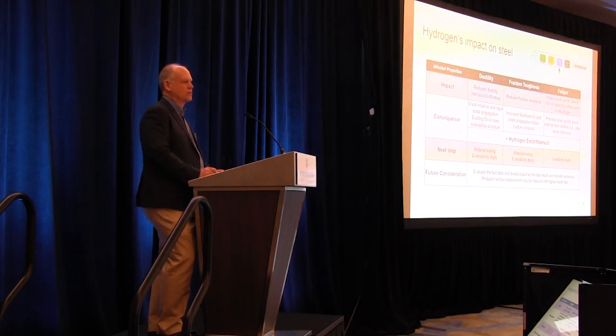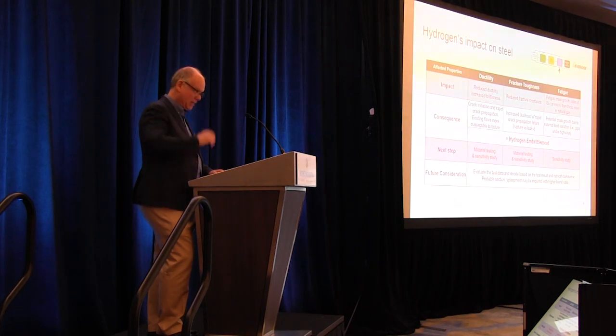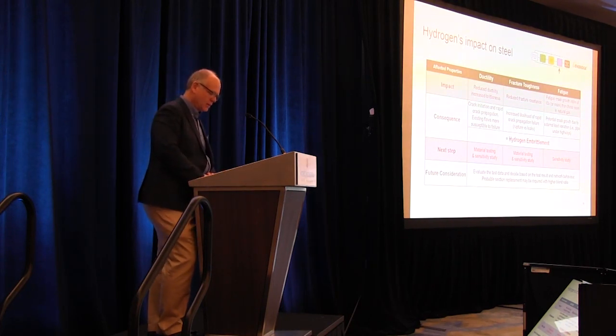And that's sort of the standard thing. Well, we'll keep the pressure the same, that'll keep the stress the same, but it really doesn't. Loading on pipelines, loading under roadways, loading from soil changes over seasonal fluctuations and so on can create changes in the pipe stress and create issues with hydrogen, even if you keep the pressure exactly constant.